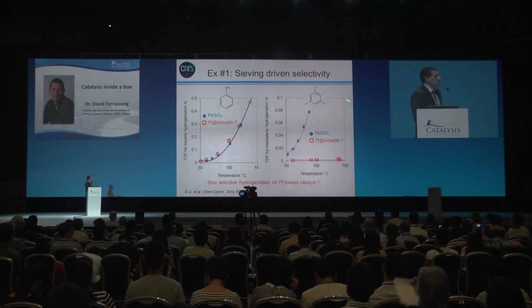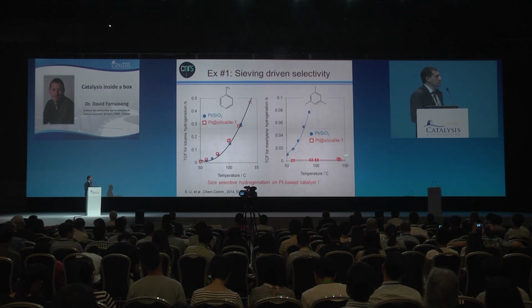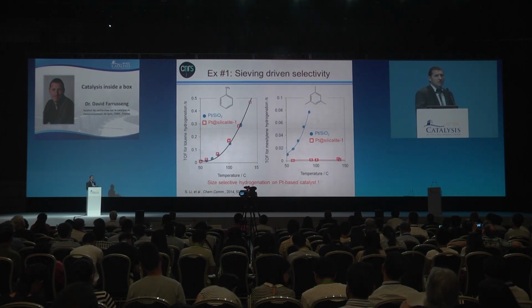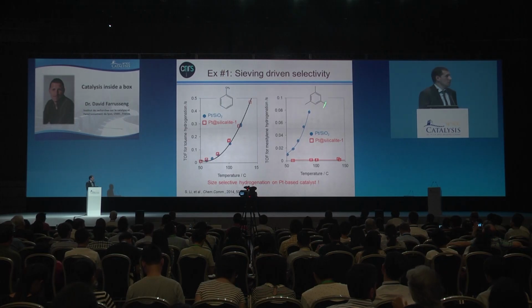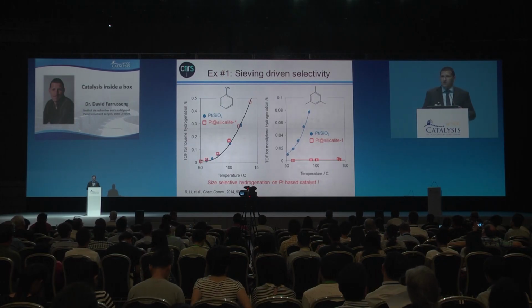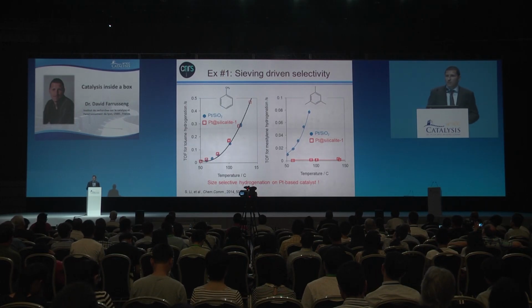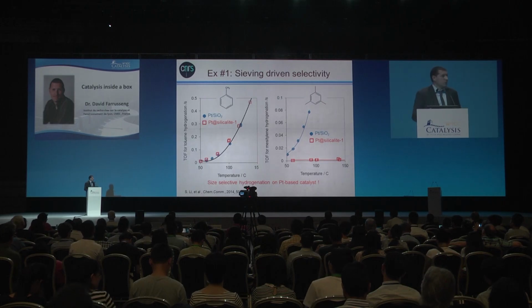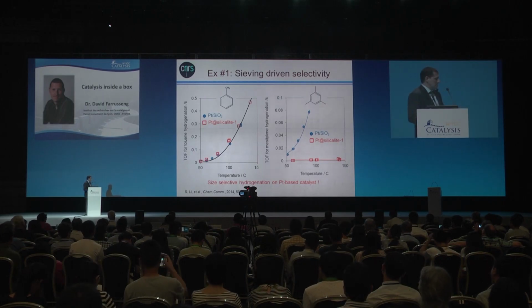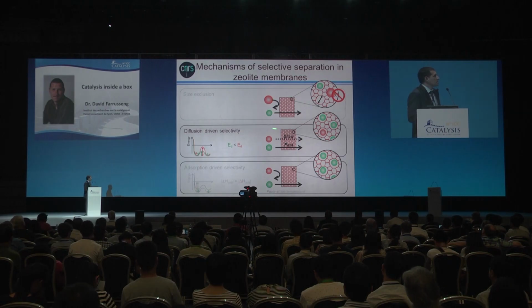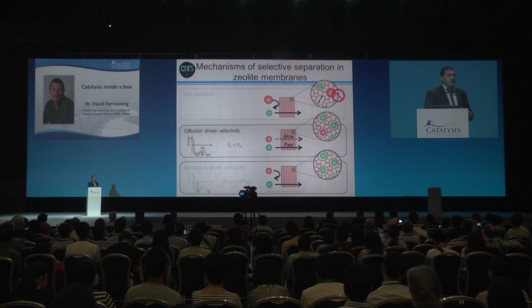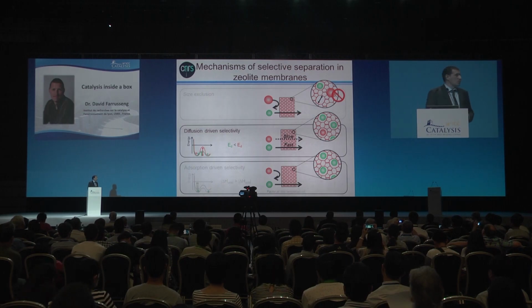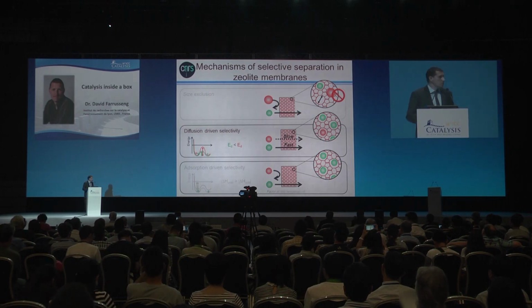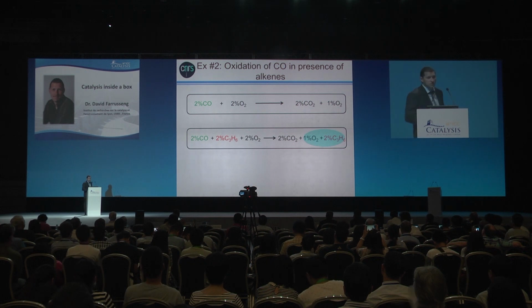In contrast, for the trimethylbenzene, you can see that our catalyst doesn't have any activity, whereas for the reference catalyst it does. So actually we have here a perfect example of the molecular sieving phenomenon. The second example is, as I told you, when the energy of diffusion of one substrate is much higher than the other, and I will address the case of the CO oxidation I mentioned a bit earlier.